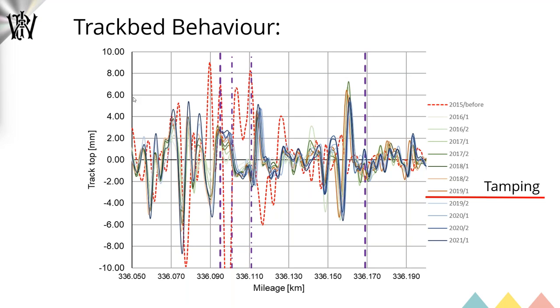What about spoiled ballast? Could that material be used for a large mixed aggregate course? About spoiled ballast, I would say that we should first try to use it as ballast again. We should try to sieve it and see what amount of ballast can be used, maybe in lower category tracks, or somewhere in sidings. As long as we can use it as ballast, we probably should. If we cannot, then I think we should crush it and use it as a sub-ballast layer. If it's now too round, then you can crush it, make it angular again, and use it in something like a 0/16 sub-ballast layer. But if you cannot do that, then yes, we should look into whether we can use it in asphalt concrete or in concrete as well, for sustainability.